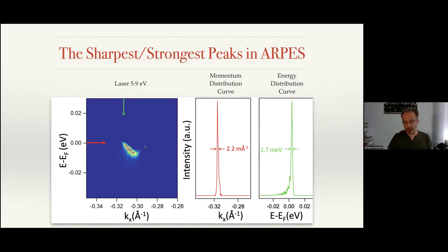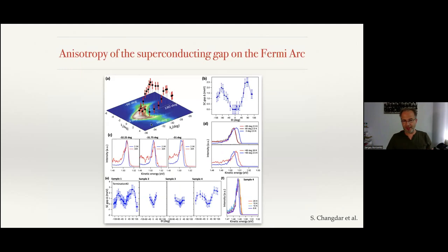Already this dispersion shows you that this is a very unusual feature, because usually photoemission data are pockets. If the shallow pockets, then the dispersion goes there. And in this case, it's kind of lost from the other side. This is the signature of the Fermi arc, because an arc is not a complete Fermi surface, just a portion of the Fermi surface. Therefore, the underlying dispersion should cross it, and then from the other side should disappear. This is the data and the precision which is achievable.